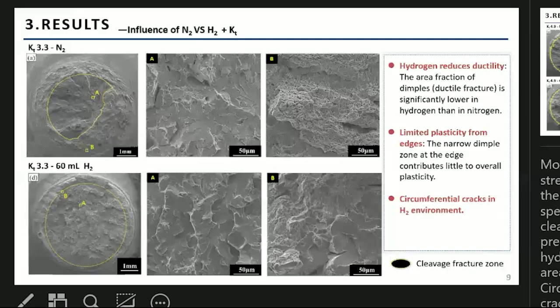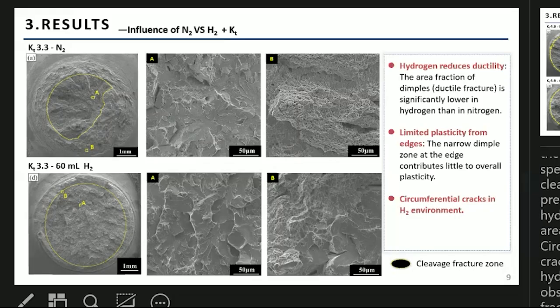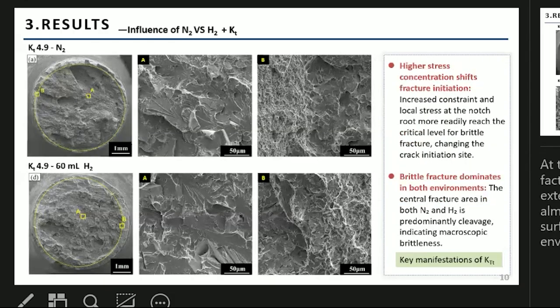Moving to the fracture surface at stress concentration factor of 3.3. In the nitrogen environment, the specimen also showed extensive cleavage morphology, indicating a predominantly brittle fracture. And in the hydrogen environment, the cleavage area is even larger. Circumferential cracks are a characteristic feature of hydrogen-assisted cracking, observed at the root edge of the fracture surface in specimens tested in hydrogen environment. At a higher stress concentration factor of 4.9, a transition is observed. Extensive cleavage morphology almost occupies the whole fracture surface in both hydrogen and nitrogen environments.